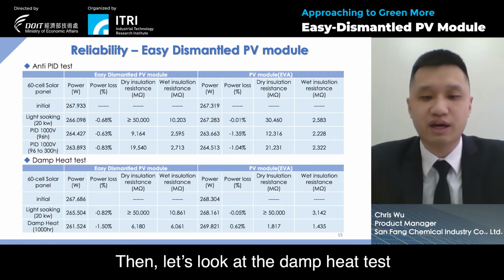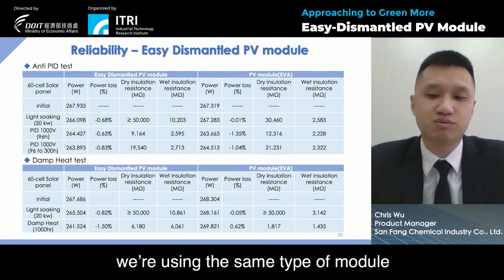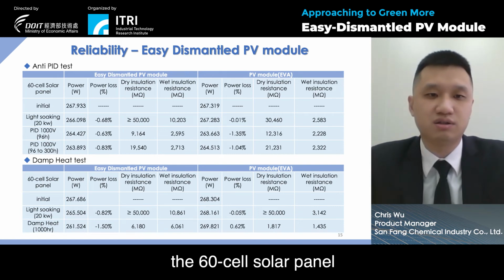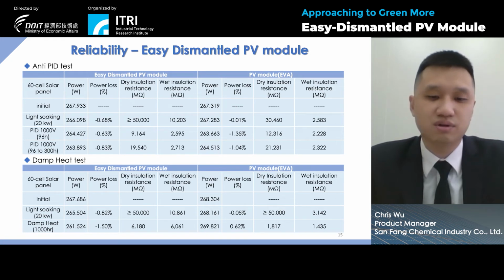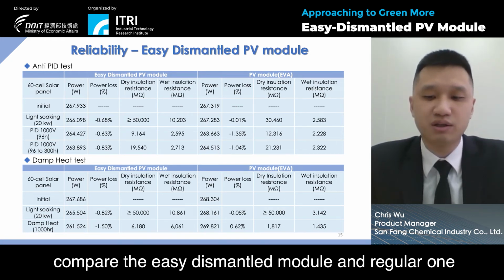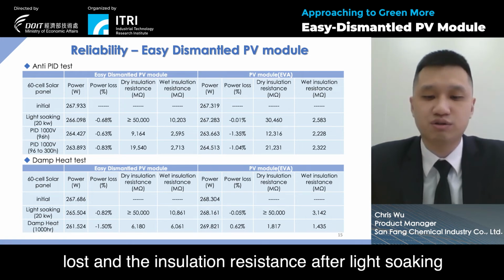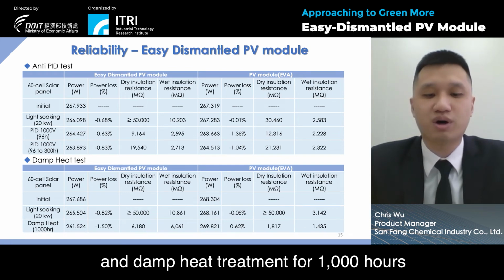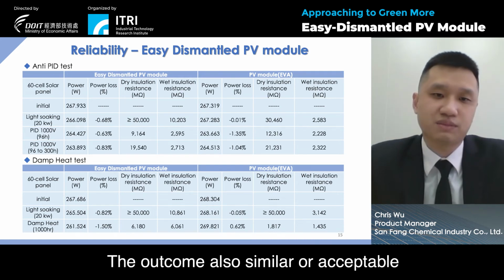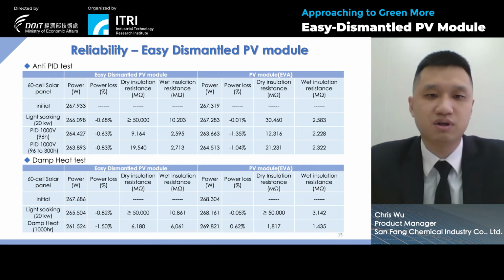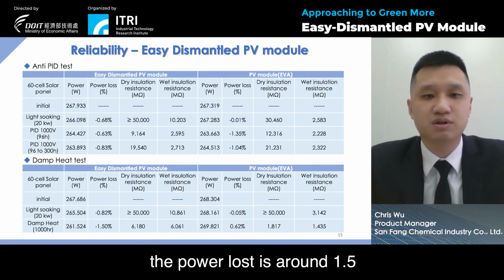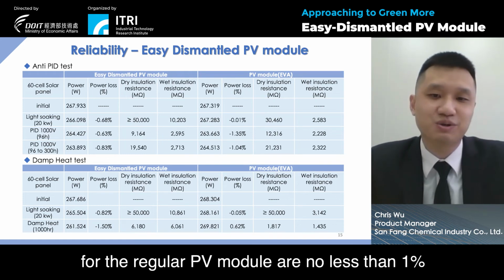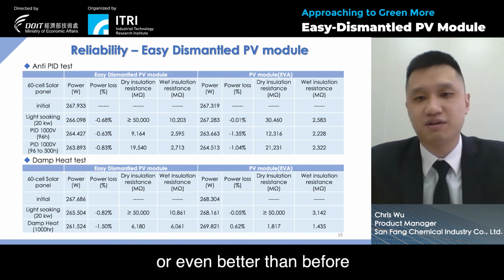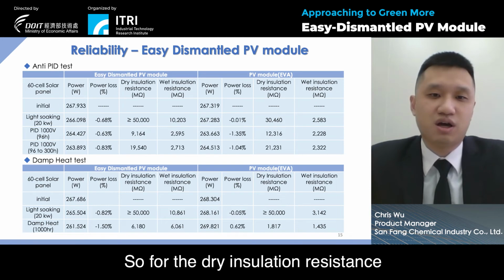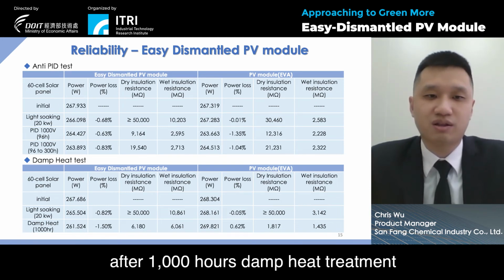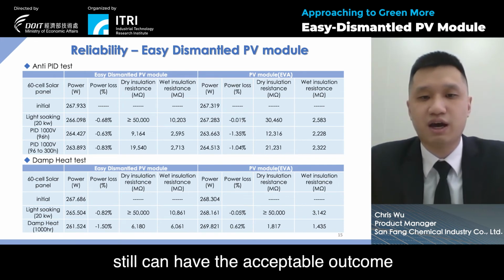So, then let's look at the damp heat test. We are using the same type of module to do the comparison, the 60-cell solar panel, comparing the easy-dismantle module and the regular one. We can see the power output loss and insulation resistance after light soaking and damp heat treatment for 1000 hours. The outcomes are also similar or acceptable. For the easy-dismantle PV module, the power loss is around 1.5%. For the regular PV module, less than 1% or even better than before. So for the dry insulation resistance, after 1000 hours of damp heat treatment, it still has an acceptable outcome.